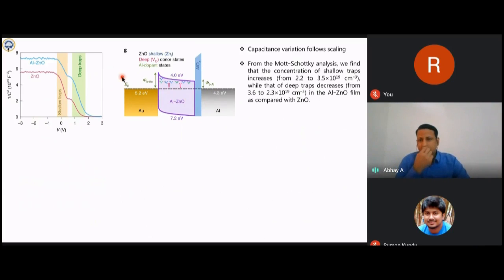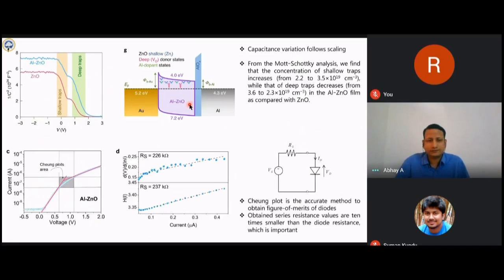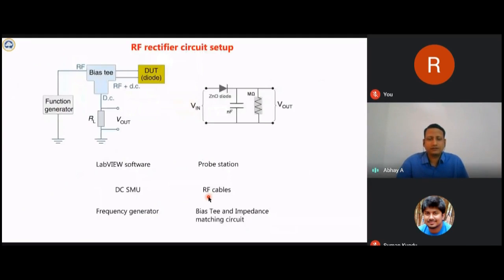So in the 1960s, there was a lot of theoretical study on this, and there was a prediction that if there are more deep states or fewer shallow states, then the wave propagation through that device will be faster. So here, by adding a small amount of aluminum, we have increased the shallow traps and decreased the deep traps, and you will see now how they benefited. The series resistance of a diode was obtained by Cheung's plot, and it is of the order of 230 kilohm, which is one order smaller than its highest resistance at the maximum voltage.